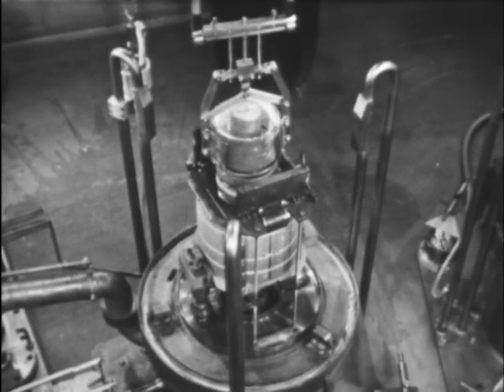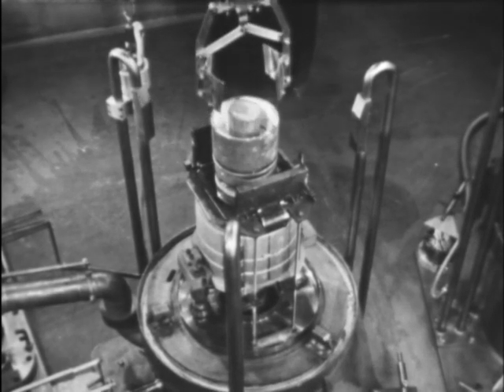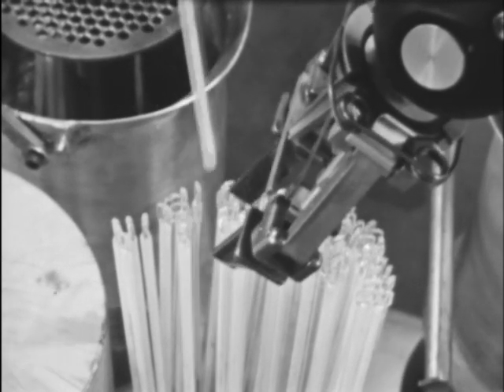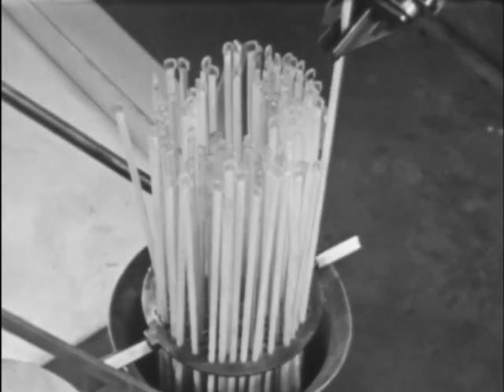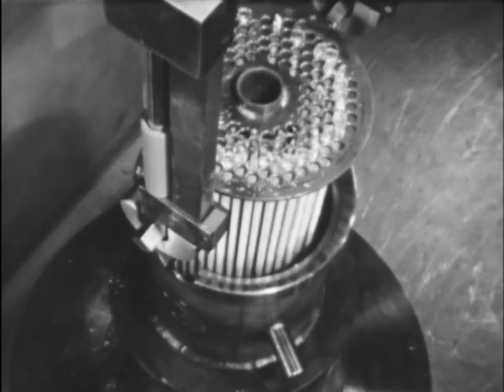The melt refined ingot is transferred to a thoria-coated graphite crucible and lowered into the induction heating coil. As many as 160 glass tubular molds, closed at one end and coated with a thoria wash, are loaded into the mold fixture.